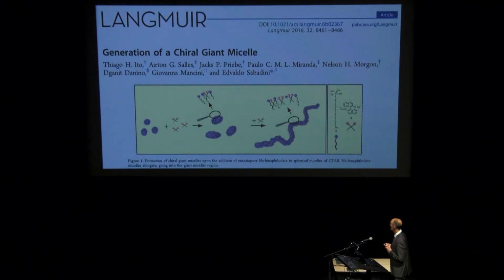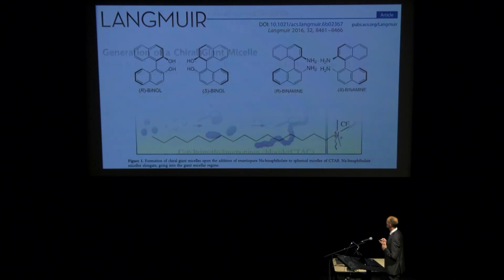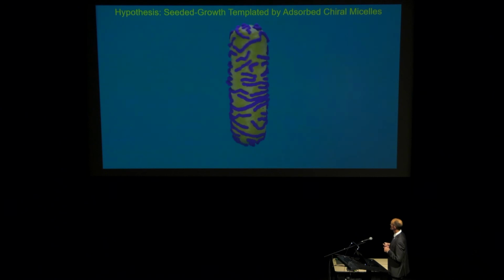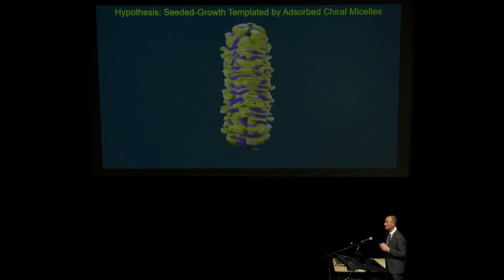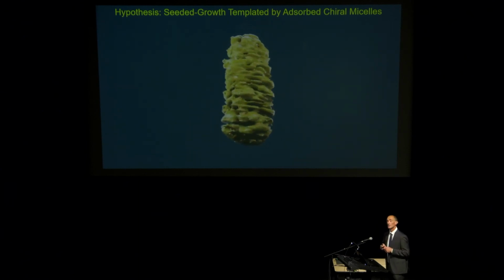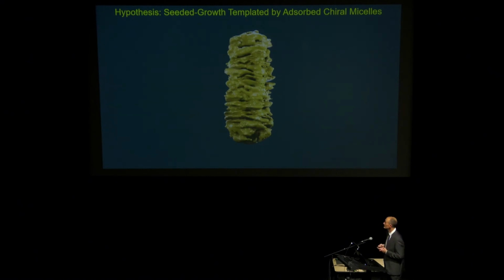And so we actually found this paper in one of my favorite journals for a long time, where they showed that, again playing with CTAB, but now introducing chiral co-surfactants like BINOL, you can obtain in solution elongated micelles that contain chirality. So they are not perfect helices, but helical micelles. And so by selecting different co-surfactants, we held the hypothesis that if these micelles can wrap the nanorods in a sort of helical manner, they might template the growth of grooves of gold that will keep the helical morphology. And of course this works, otherwise I wouldn't be showing you this in this lecture.